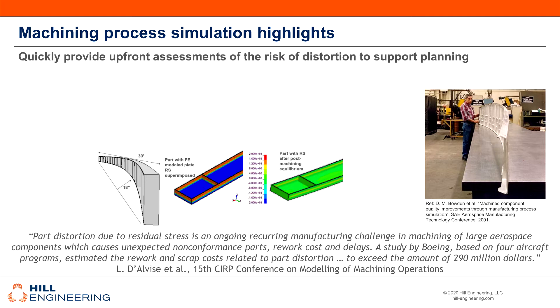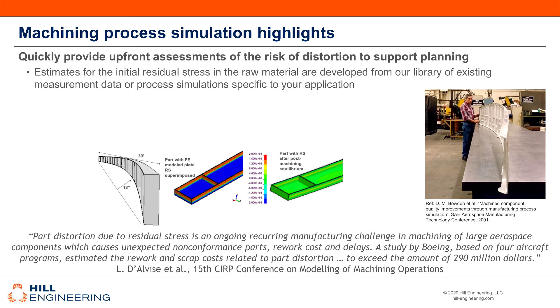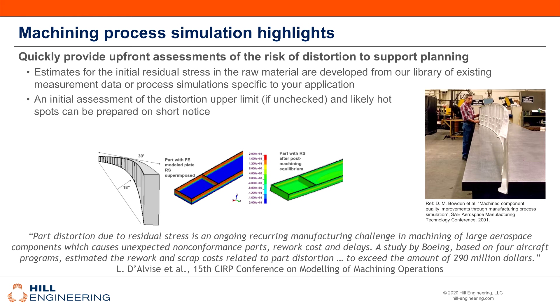Wow, that could cause some issues. How would you go about addressing a problem like this? We start with estimates for the residual stress in the raw material, which we might get from our library of existing measurement data, other process simulations, or residual stress measurements specific to the application. Once we have that, we evaluate the machining plan that the customer has in mind and provide distortion estimates. So you are able to recreate this result using your simulation. That's correct.